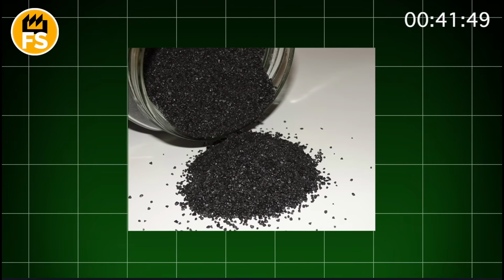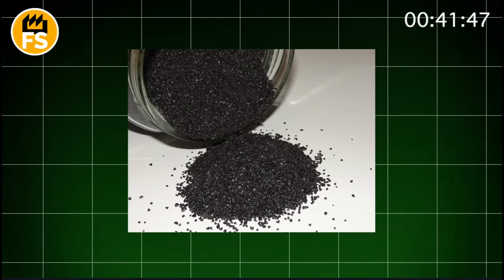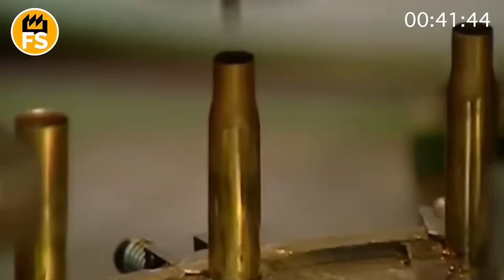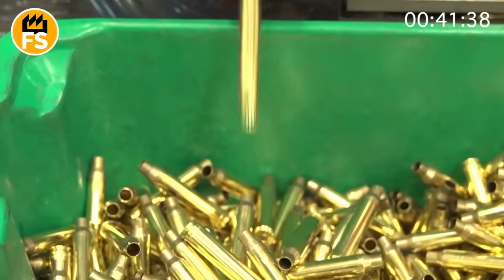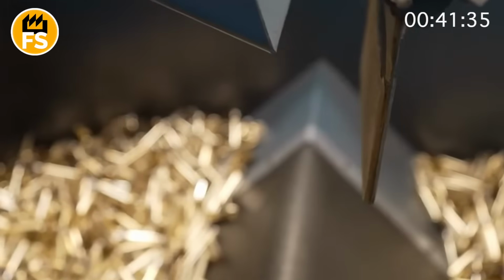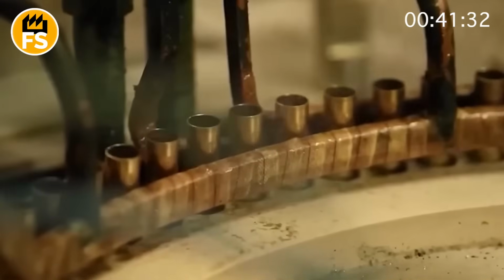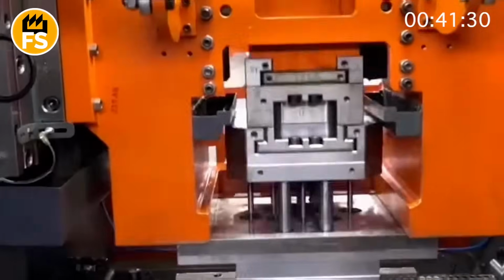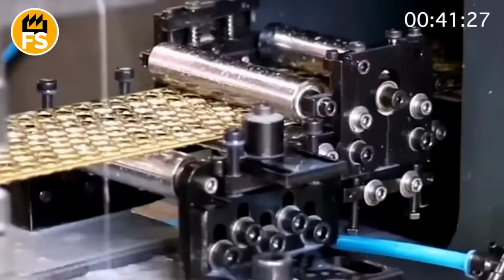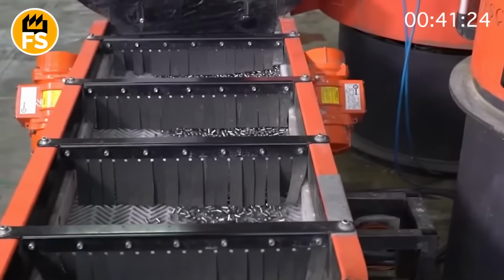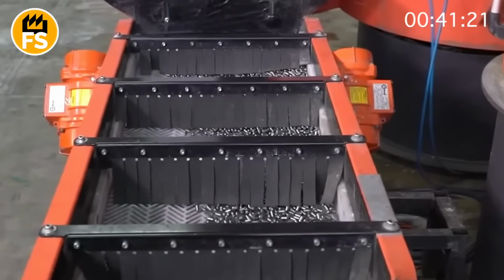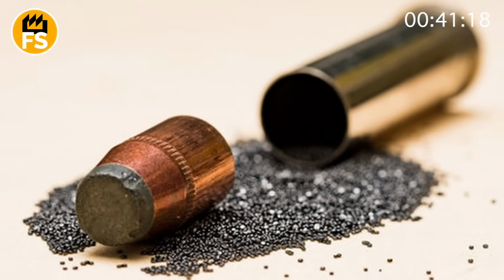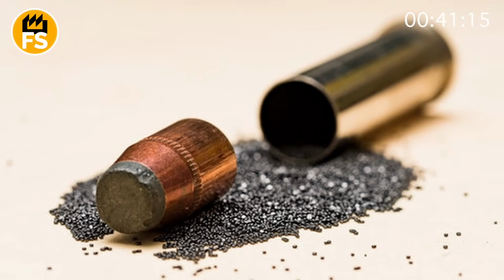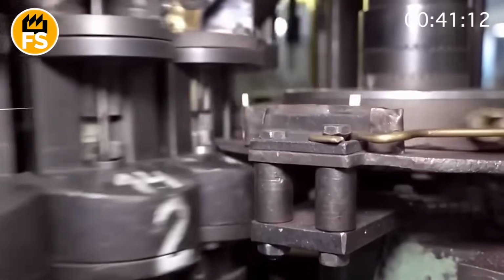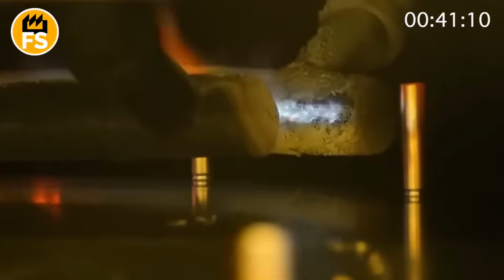Next, gunpowder. The type depends on the ammunition's purpose. For pistol rounds, most often spherical smokeless powder. For rifle rounds, extruded powder in the form of small tubes. On average, one .223 Remington round contains about 24 grains of powder. For comparison, a .45 ACP round contains only 5 or 7 grains. Gunpowder is measured automatically to the thousandth of a grain. Too much or too little is a danger to the shooter and the weapon. An error of 1/10 of a grain is unacceptable. Some systems use real-time optical scales that react even to vibrations in the workshop.